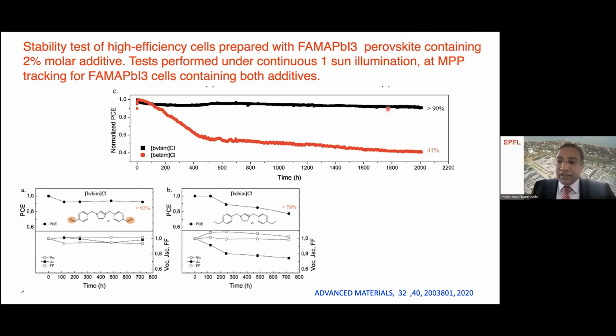With the polymerizable ionic liquid, the stability data over 2000 hours shows the decrease in efficiency is around 10%. At the same time, with a similar ionic liquid, just focus on the two structures at the bottom, one highlighted with yellow, that's a polymerizable ionic liquid. And the second one is a similar ionic liquid, but with a saturated carbon. If you look at these differences in the stability data, with the polymerizable ionic liquid the performance is extremely stable. On the contrary, the similar ionic liquid without the double bond that polymerizes gives you much lower performance. It's 40% of the original efficiency.